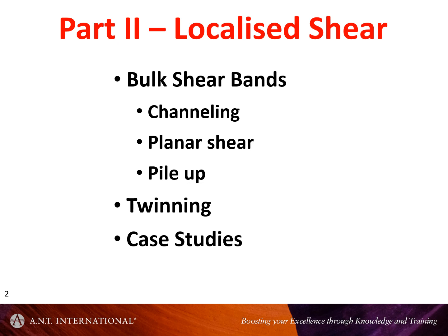So when it comes to localized shear on the microscopic scale, in fact, there's quite a bit of ambiguity about how people describe it. There is such a thing known as channeling, which is very well understood, in fact. And that gets confounded often with what is planar shear, which is just simple dislocation slip on a given plane. And that then leads into confusion about what could contribute to a phenomenon known as pileup, which is basically an amplification of the stress at the head of a slip band where it intersects a boundary or some other barrier.